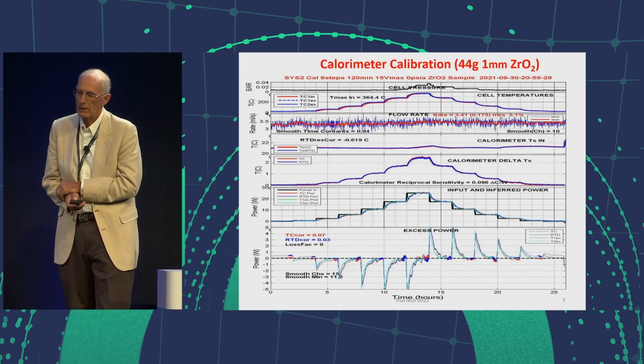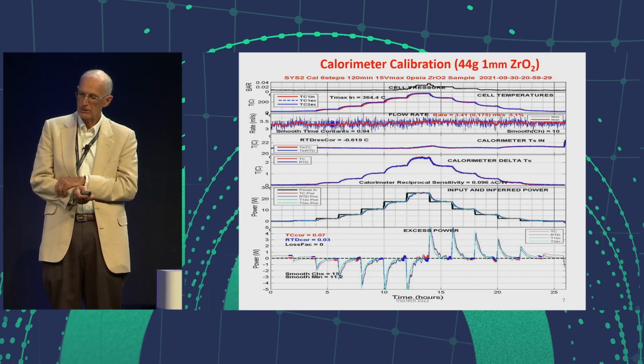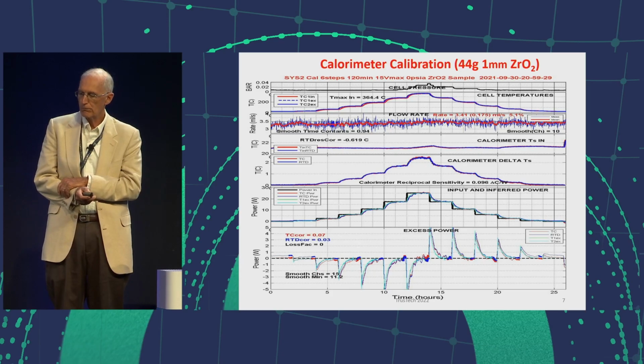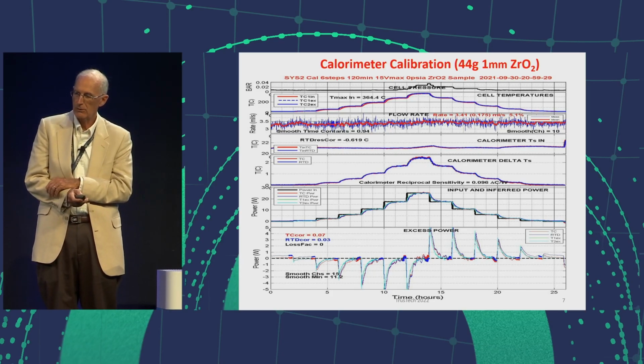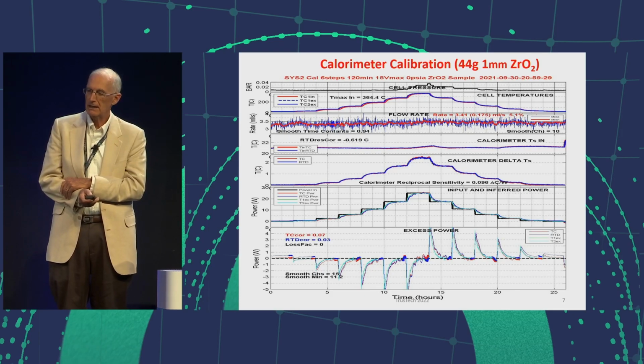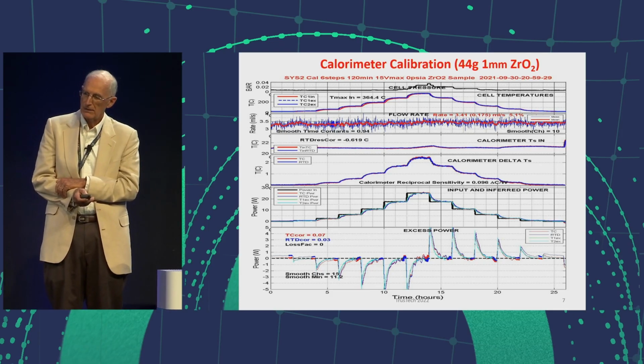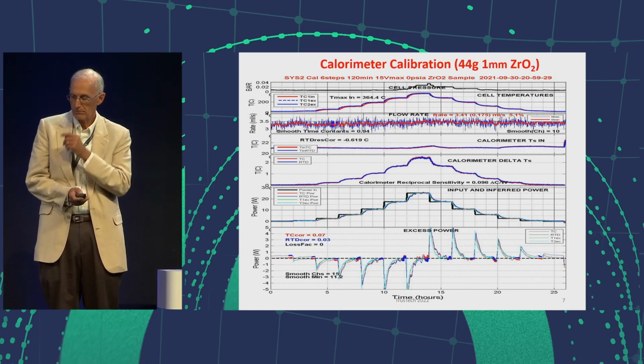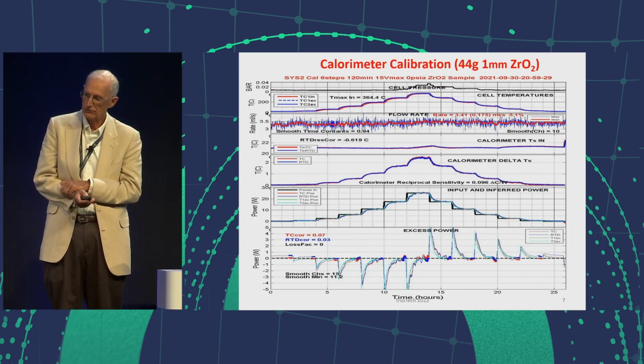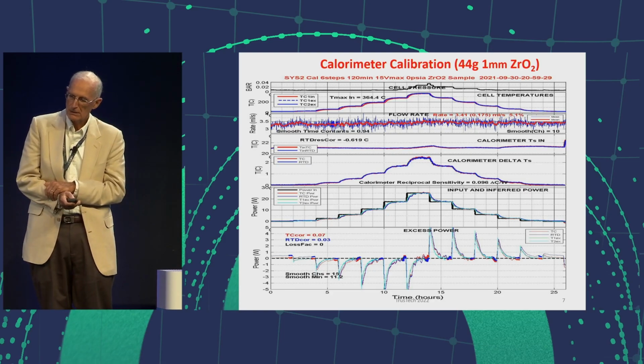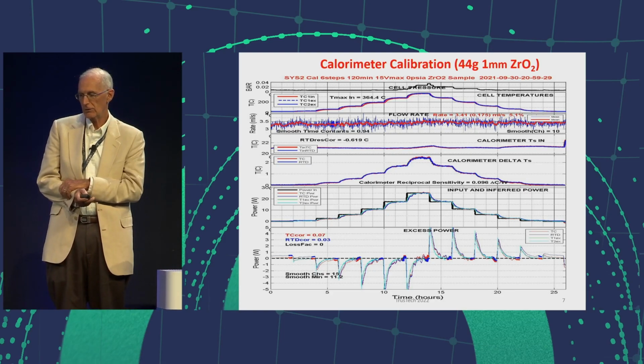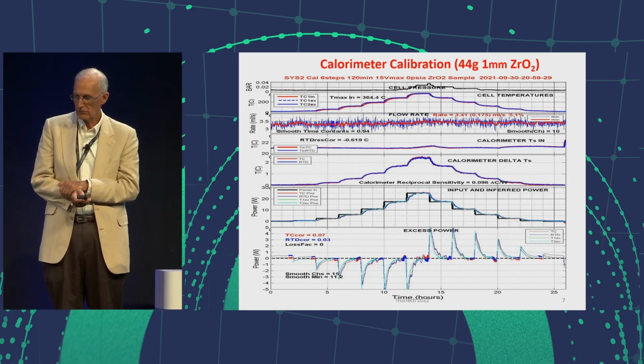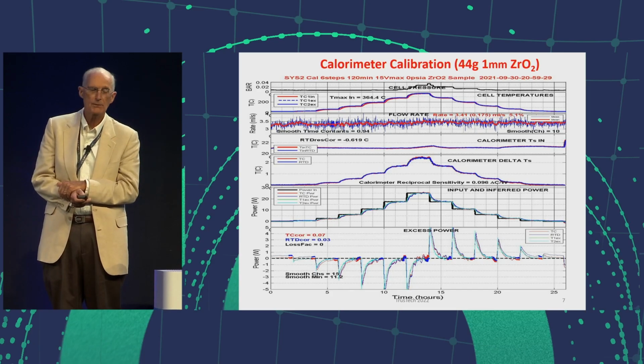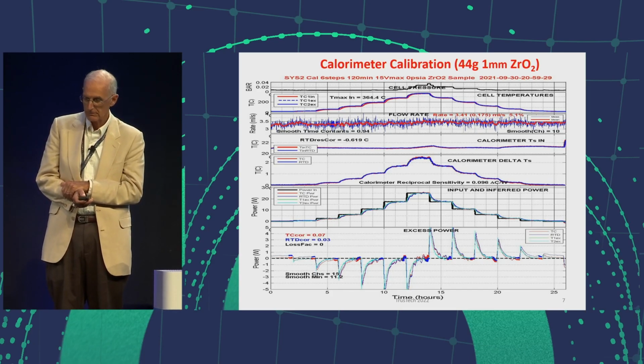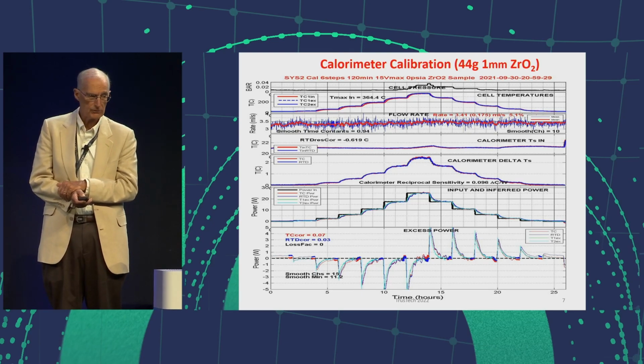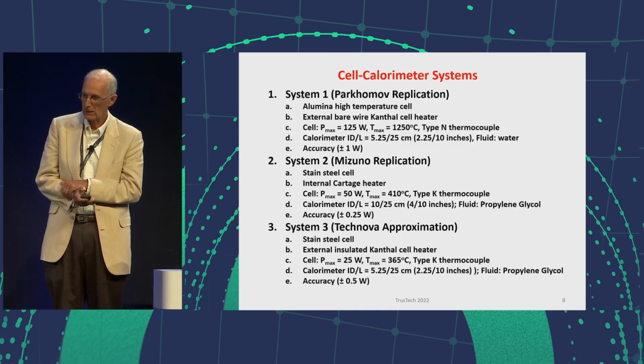The fourth graph plots the inferred thermal powers for the input power. The black line and the sharp lines are the input power. The inferred powers are the curved lines from both of the temperature sensors. And if you subtract the two, you will see that you should be getting zero excess heat, which is the zero there. And you see there's about an hour to hour and a half time constant to read accurate temperatures. In this particular measurement, the accuracy was about plus or minus half a watt.